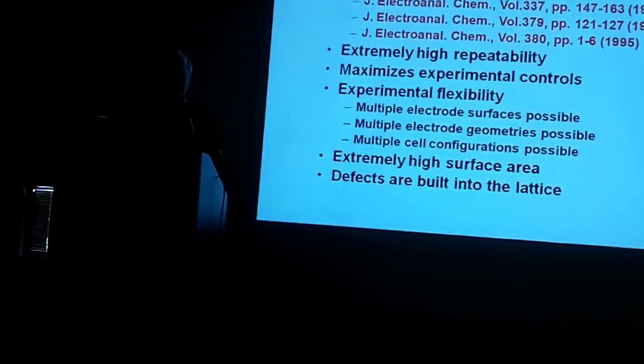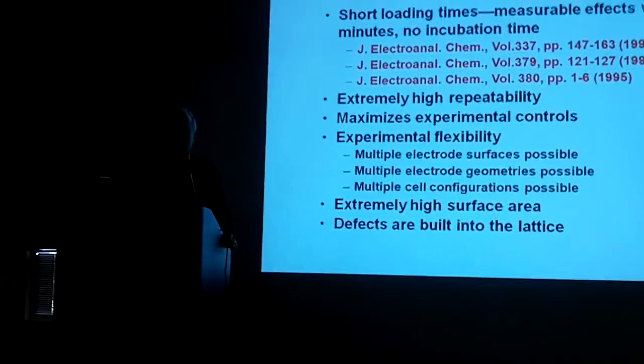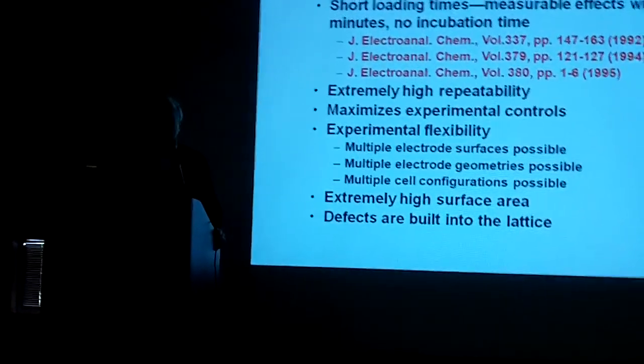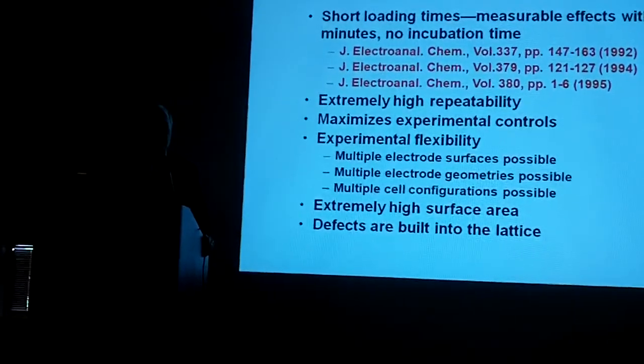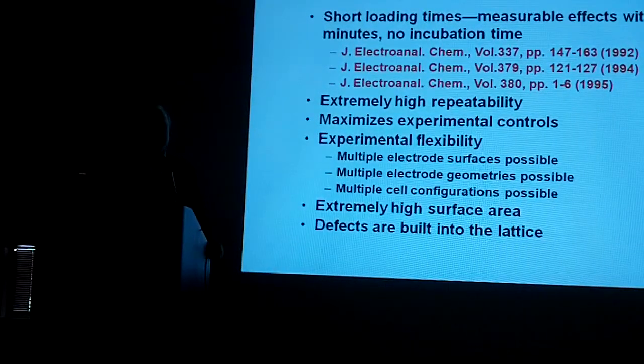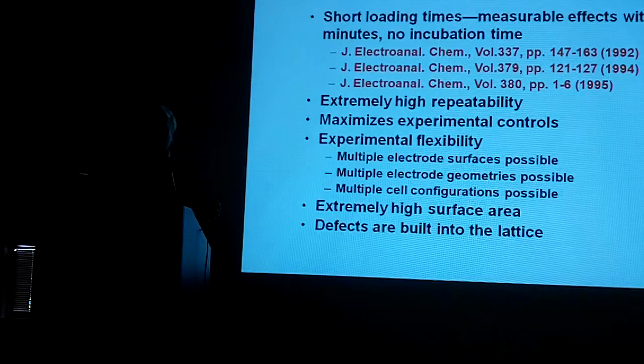Various experiments, starting with palladium foils, trying to get extremely pure and things like that, we've discovered now that a few defects, in fact, may actually help the process. In this case, the defects were built in. Was it because of the deuterium going in there that caused the defect, or what? But in any event, these two things we now understand are extremely critical in the reproducibility of the experiment.